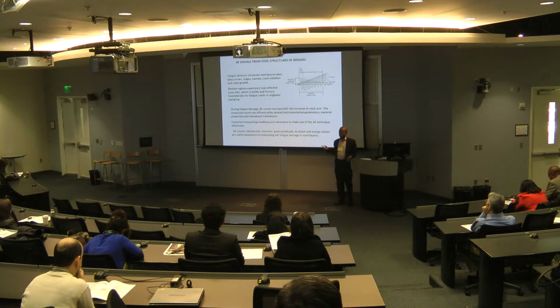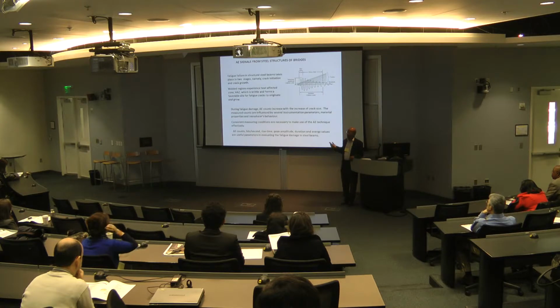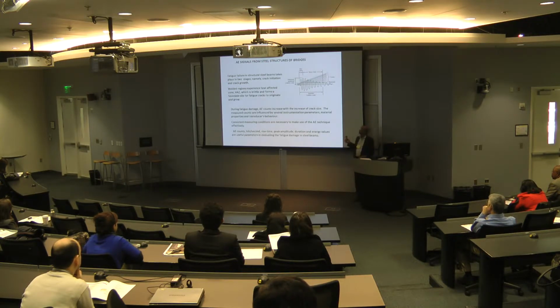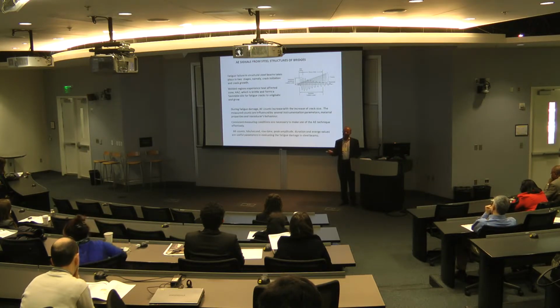And this is something about the acoustic emission. Acoustic emission signal comes out as a burst. Whenever there is a propagation, it's going to give rise to a signal. Each burst can be quantized by identifying one of these parameters indicated in the diagram, like rise time, peak amplitude, the duration of the pulse, etc. We have to set the minimum threshold level below which we will ignore the signal. In that way, we can avoid the effect of ambient noise.